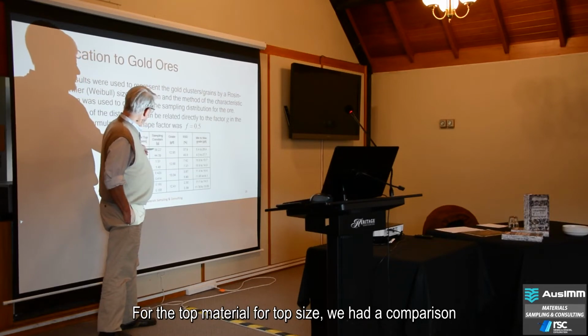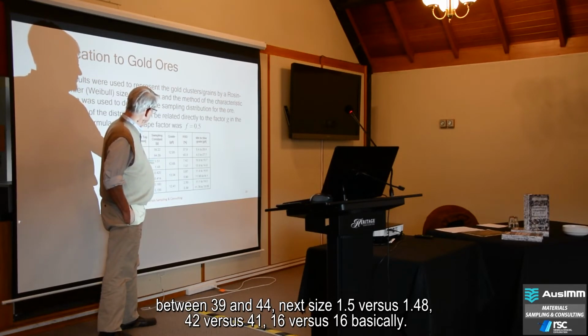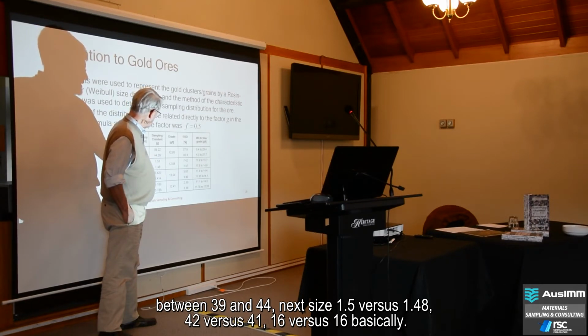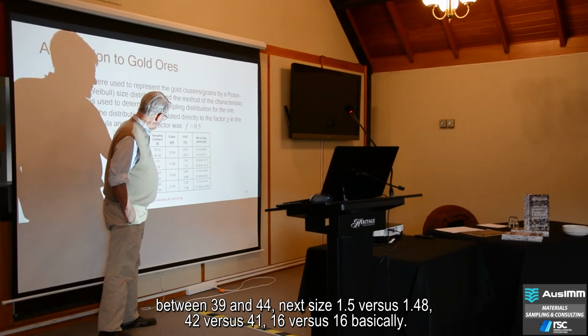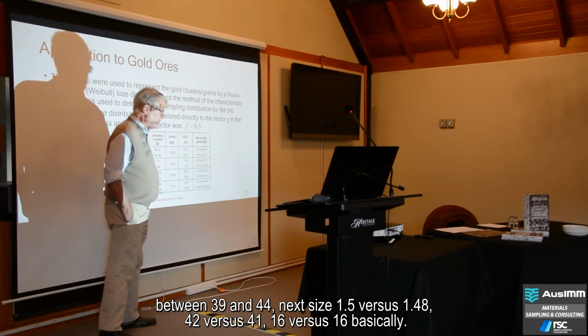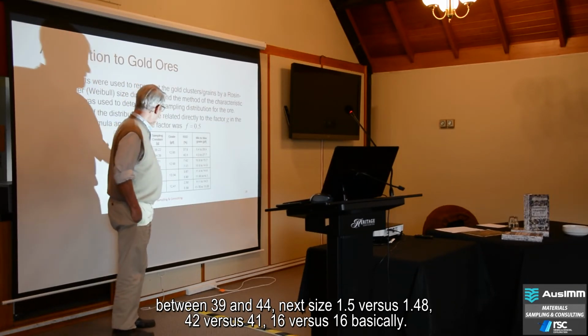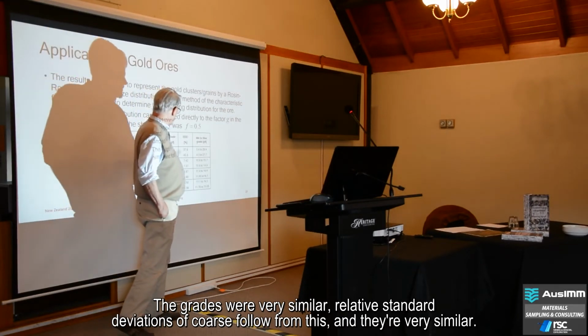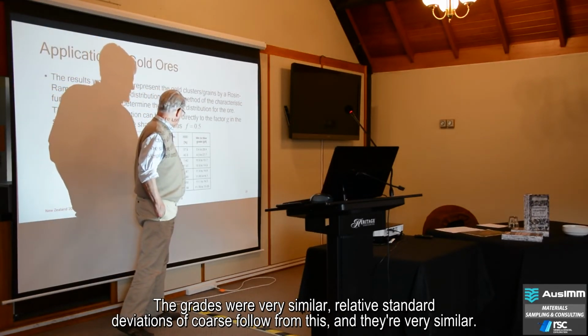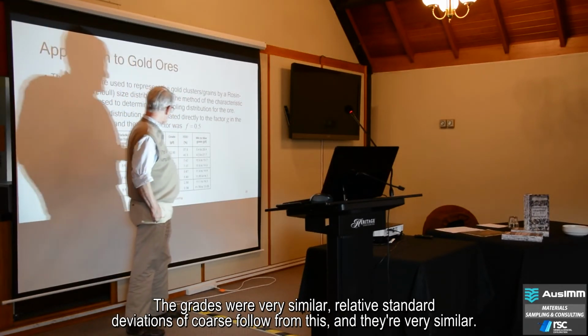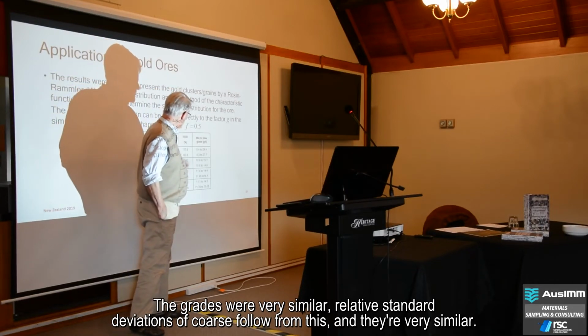And so for the top size, we had a comparison between 39 and 44. Next size, 1.5 versus 1.48, 42 versus 41, 16 versus 16 basically. The grades were very similar. Relative standard deviations, of course, follow from this, and they're very similar.